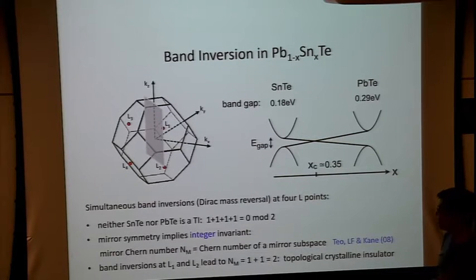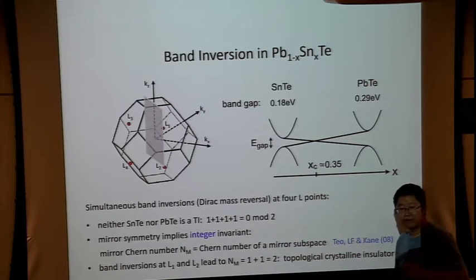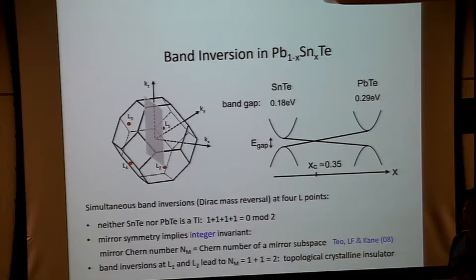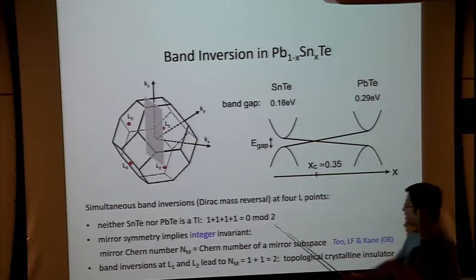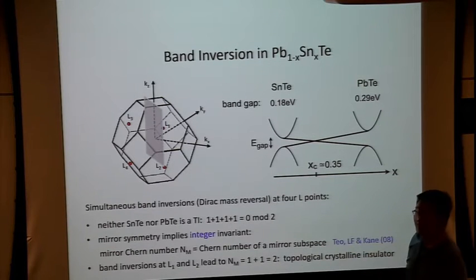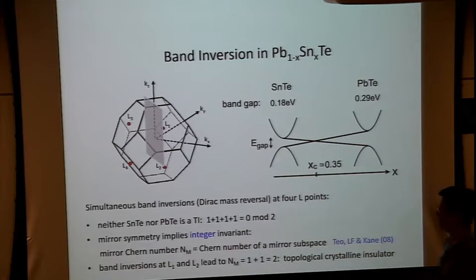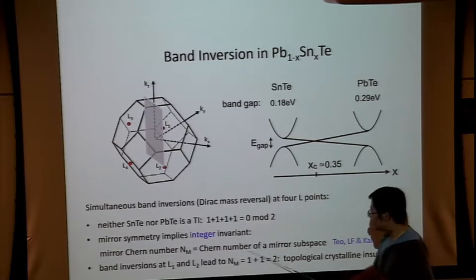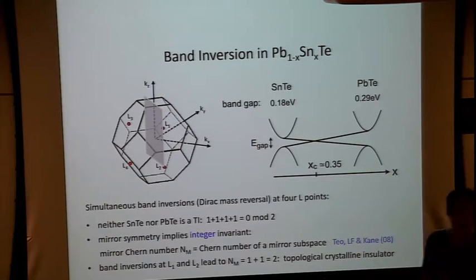On the other hand, in contrast, for a time reversal invariant topological insulator, the index is a Z2, a binary quantity. In that case, if you take into account the four band inversions, it adds up to 0 mod 2. That's why it's not a topological phase with time reversal. Later, I will show that if we go beyond the framework of non-interacting electrons, the topological indices associated with phases protected by reflection symmetry are not integer, but Z8. It has to do with effective interactions. Okay, but for now, let me just stick with the band theory.